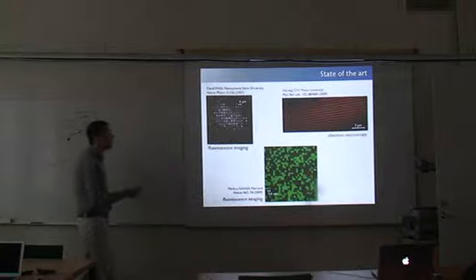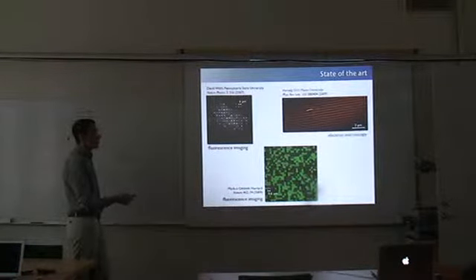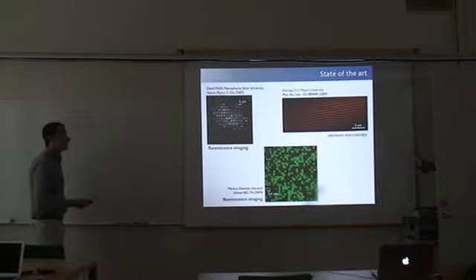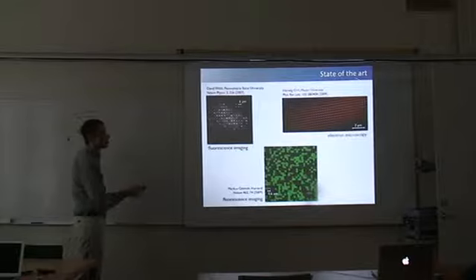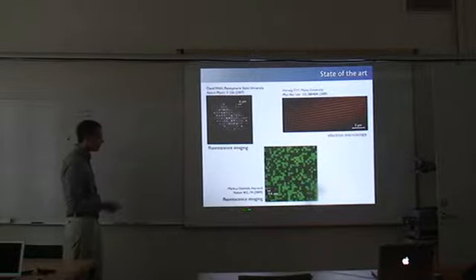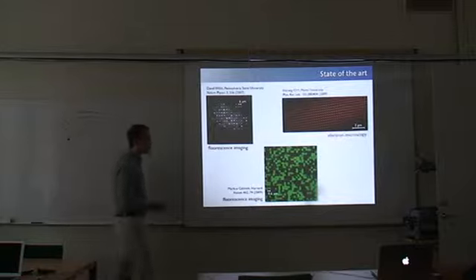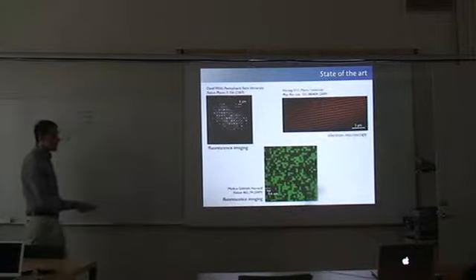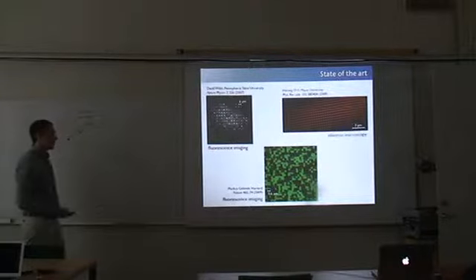It's not single atoms you're seeing here. It's really something like 100 atoms, and also the image is averaged over 100 images to get this kind of quality here. So it's not single atom sensitive yet, but it's a beautiful method and has very nice high resolution. So the first one now, Markus Greiner in 2009, showed that you could take this method from Dave Weiss to very high resolution imaging by just using much higher resolution microscope objectives, and to image single particles in these lattices, which have now a spacing of the order of 500-600 nanometers, which is just the system we want to use in the experiments.